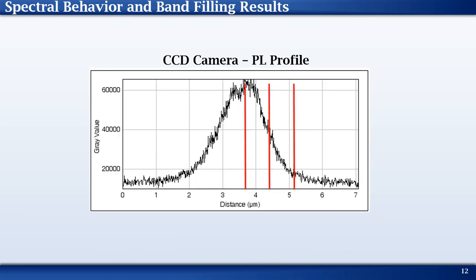At the beginning, I mentioned there being a redshift with increasing position in steady state field measurements. This figure depicts the PL profile showing the three positions where the streak camera measurements were performed. A careful analysis shows that those observations are not related to the redshift in the waveguided photon spectrum due to photon recycling, but instead due to bandfilling.